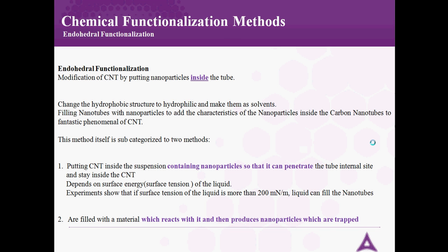As scientists show, depending on the surface tension of the liquid that we are putting carbon nanotubes in, if it's more than 200 millinewton per meter, it can go inside. The liquid can fill the nanotube, otherwise it's not possible to do this procedure.